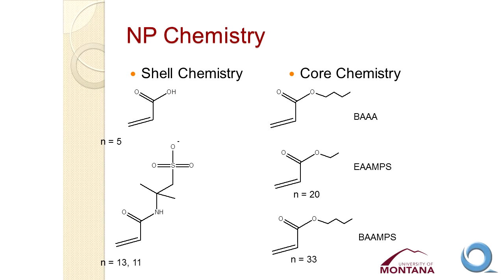We've done this with a lot of different chemistries now. We started off with acrylic acid as the shell chemistry and butyl acrylate as the core chemistry. We've moved on to AMPS, or acrylamidomethyl propane sulfonic acid, as the ionic monomer, and we now have methyl, ethyl, and butyl acrylates as the core for the nanoparticles.